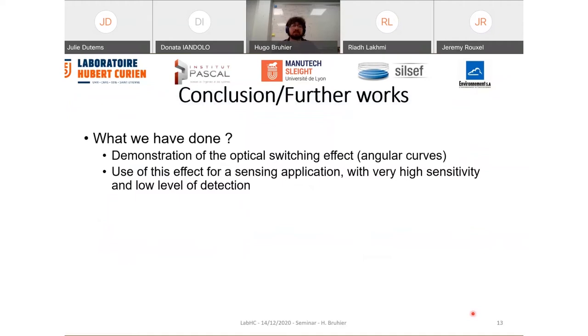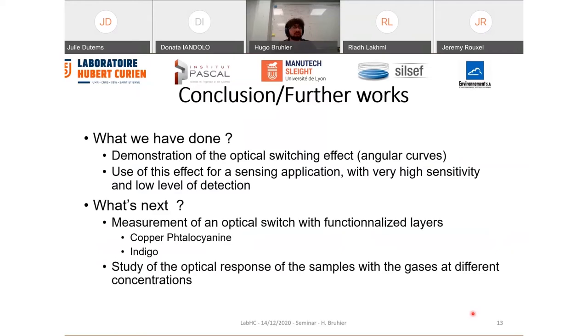And so what's next? The measurements of the optical switching effect with functionalized layers developed by Institut Pascal, with a copper phthalocyanine layer for nitrogen dioxide and indigo layer for ozone, and also the study of the optical responses of the sample with gases at different concentrations, and so a deeper study of the interaction between the gases and the functionalized layer with a plasmon.